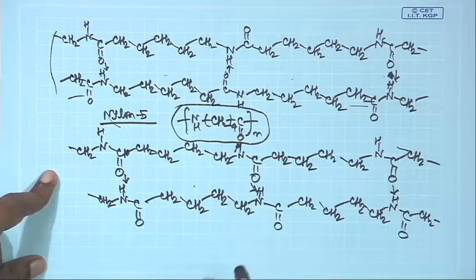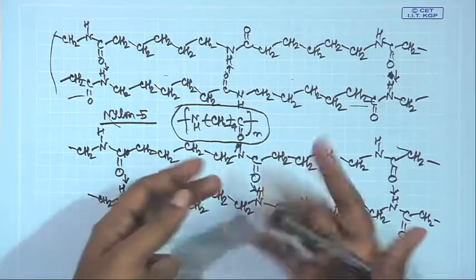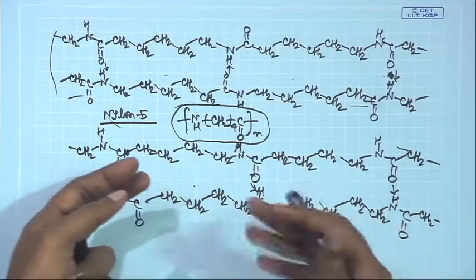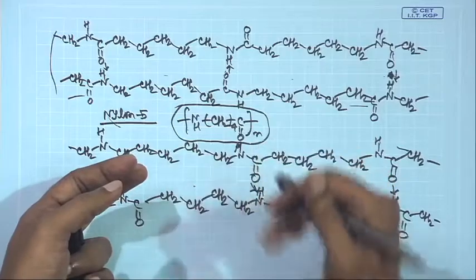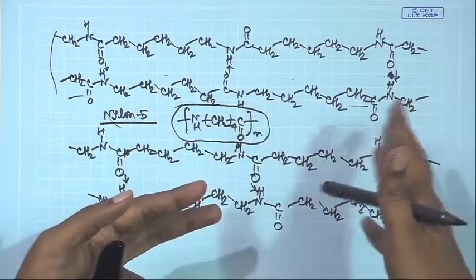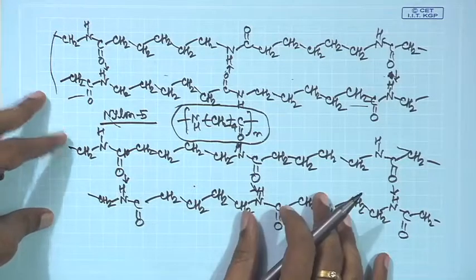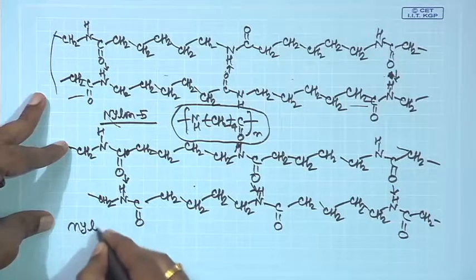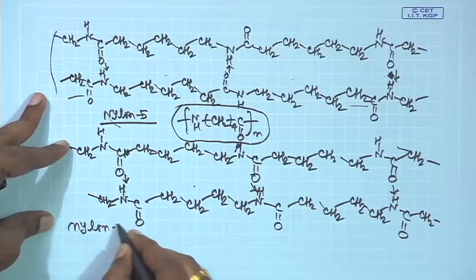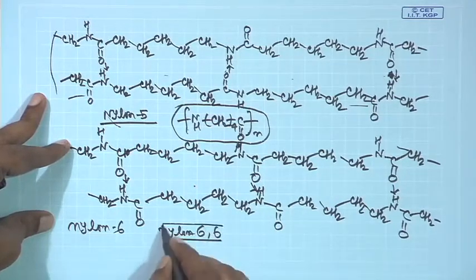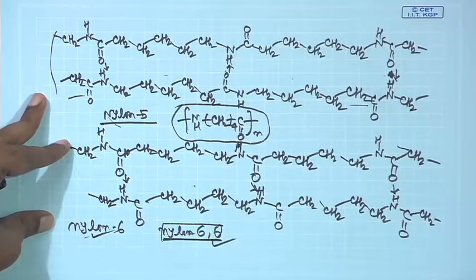That is the reason why if you have an odd number of CH2 units between your amide groups, the system will have a lower melting point and percent crystallinity compared with a nylon which has an even number of units. So, nylon 6,6 has a higher melting point and higher crystallinity than nylon 6, because you have an even number of carbon atoms between the subsequent CONH groups.